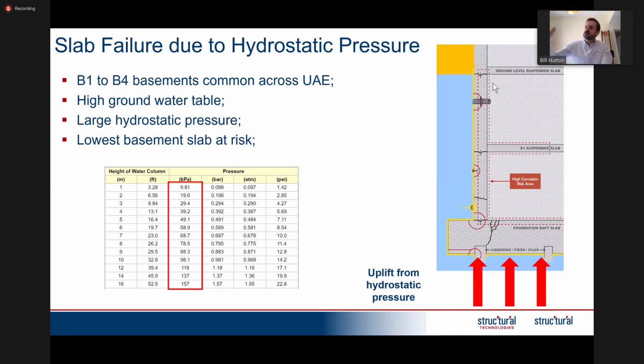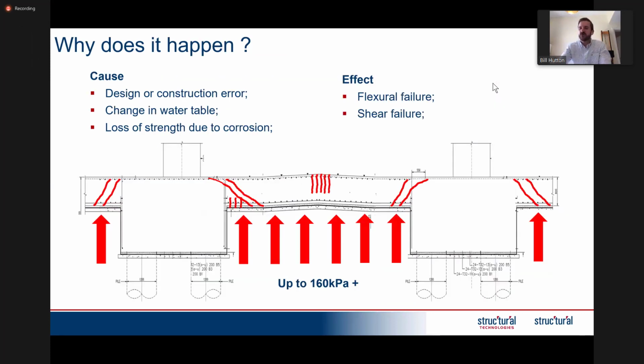So if you actually excavate the soil around the building, probably 1.5 meters, you would reach the water table, which means that you have a very large hydrostatic pressure, which could range from 10 to 160 kPa. This represents a diagram where you can see the slab and pile caps. This would represent the lowest level of a basement. This huge hydrostatic pressure can cause the slab to bend, which can result in flexural failure or shear failure at the connection between the raft and the pile cap, and can cause a lot of excessive cracking, which can result in durability related problems, and of course ultimately failure of the raft.